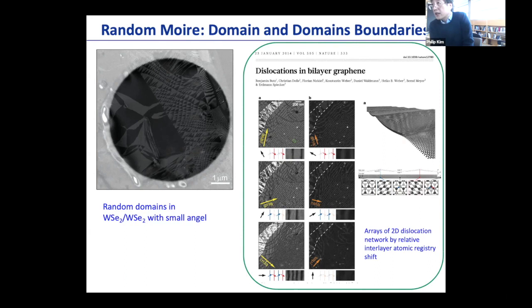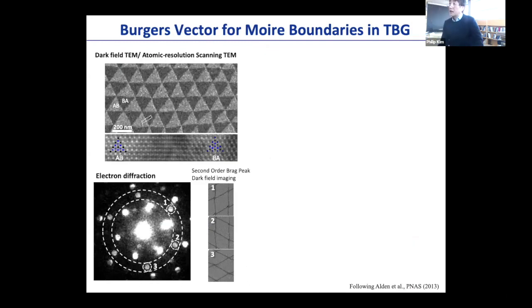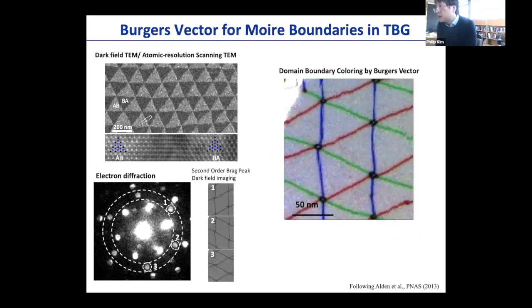But the other thing we can mention here is that this type of Moire pattern formation, or this structural disorder, is also an opportunity for experimentalists, because it can be analyzed in terms of new types of structures. Not only electrically as a fold of the band, but structure-wise, this Moire pattern can be interpreted as the combination or junctions of structural dislocation lines, where especially in twisted bilayer, there is a topologically protected 1D mode running along these Moire lines. And it turns out that when you investigate the dislocation line network, or this 2D dislocation network, another way of interpreting this Moire lattice, it is a strongly topologically protected object.